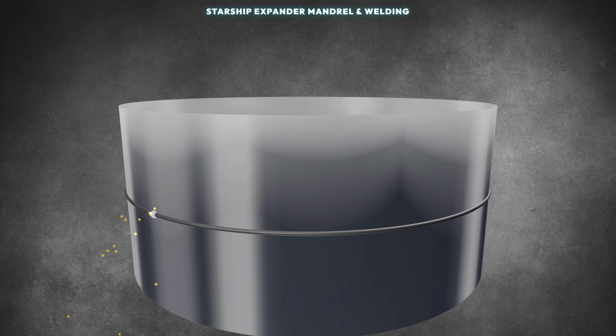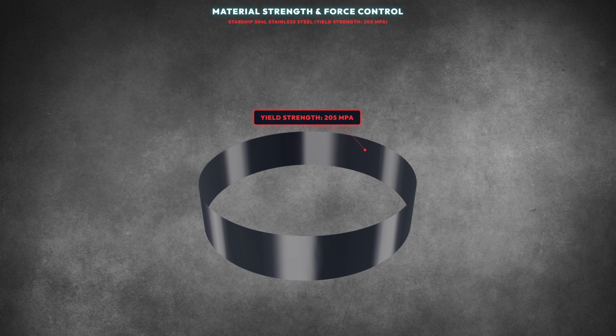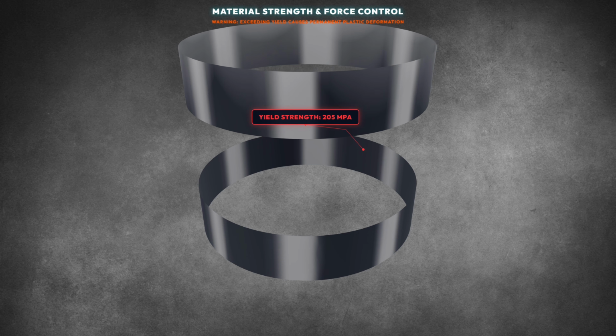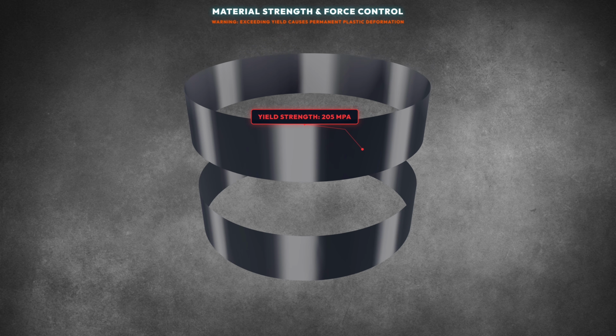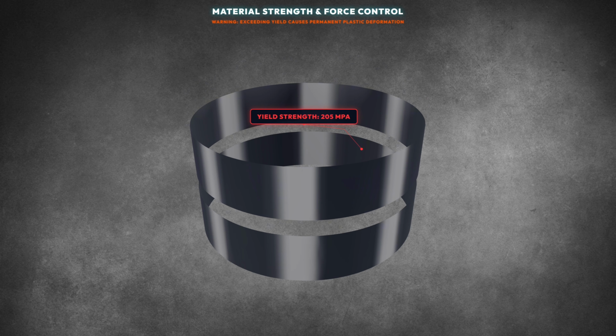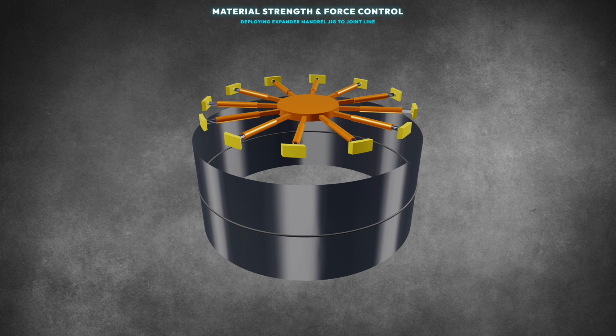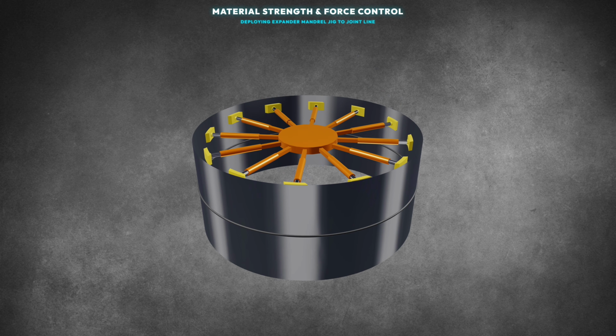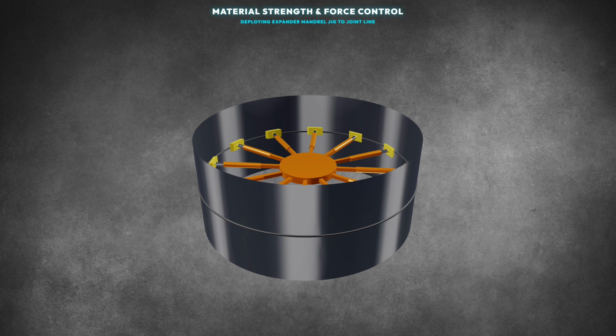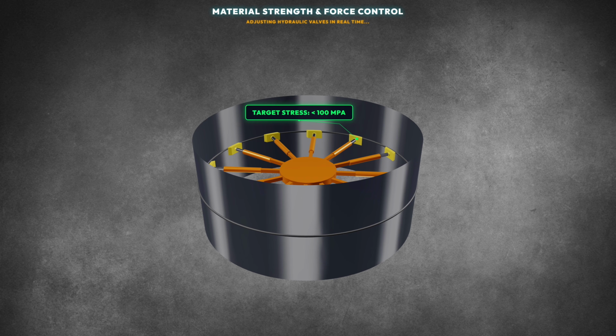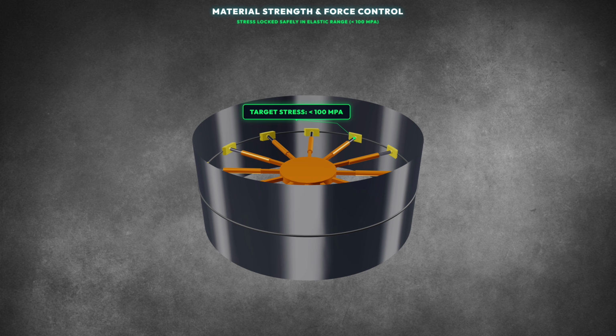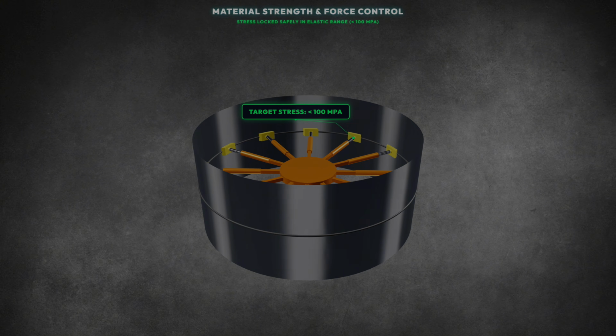However, expanding the ring requires extreme control. Per AISI material certifications, Starship's 304L stainless steel has a yield strength of 205 megapascals at room temperature. Exceeding this critical limit causes plastic deformation, stretching the steel permanently and ruining the vehicle's diameter. Therefore, the system's proportional hydraulic valves adjust pressure in real time. The goal is to keep structural stress below 100 megapascals, staying safely within the elastic range.